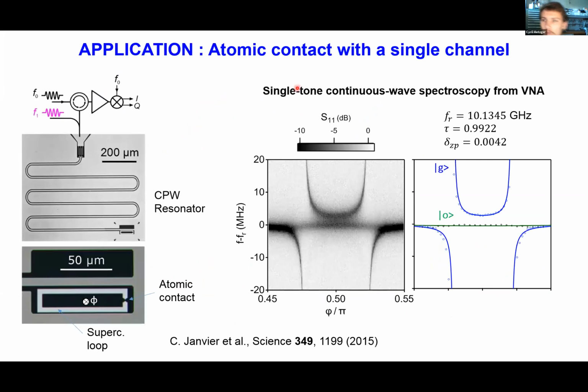Now let's see how we can apply this to understand data that was obtained with atomic contacts with a single channel. So the atomic contact was embedded in a loop that was coupled to a lambda/4 resonator measured in reflection. And I'm showing you here on this left plot the magnitude of the reflection coefficient as a function of the phase difference and the frequency of the measurement tone. And in this case, we had an Andreev transition anti-crossing the resonator. And for each phase flux value, we extracted the position of the frequency, and we could fit this very well with the theory. And in this case, the generalized Jaynes-Cummings description was enough. And you can see that in a significant part of the time, the system also resides in the odd state. And in this case, the resonator is not shifted, and you can access its bare resonance frequency.